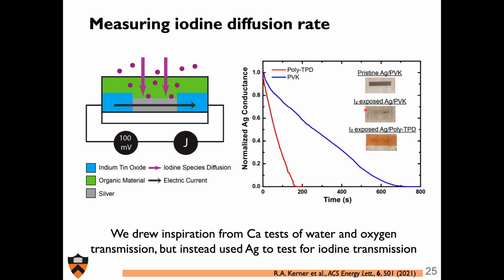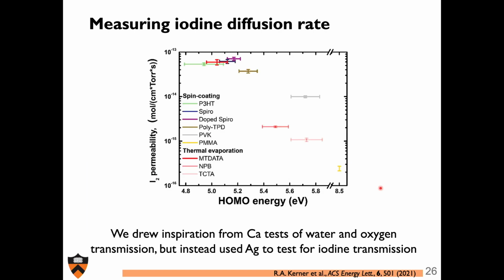Taking two examples here, here's poly-TPD, a shallow HOMO polymer. You can see it becomes non-conductive within 200 seconds. And PVK, a much deeper HOMO polymer, holds on substantially longer. You can fit these transients to understand the diffusion coefficients in these systems, or iodine permeability, as it were. And what we see is that shallow HOMO organics, whether they're small molecules, thermally evaporated, or polymers, spin-coated, anything that's shallow, you have quick diffusion of iodine. Anything that's deeper, you have much slower diffusion.